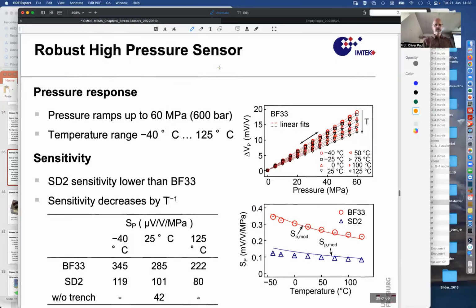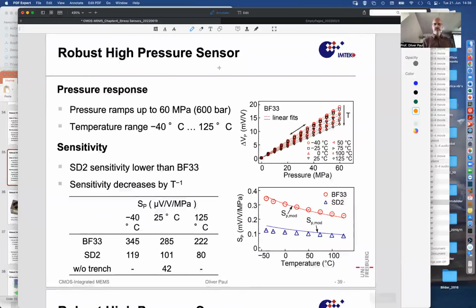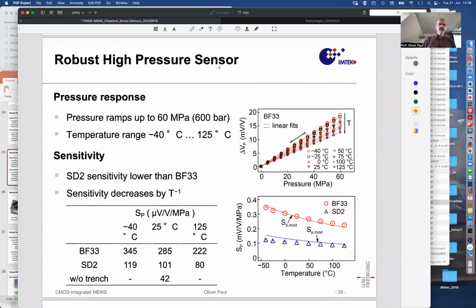Then, of course, many other aspects are studied in such a PhD thesis. Like, of course, now the linearity is a question. So if we go to 60 megapascal, 600 bar, is the sensor linear? And here's the pressure, and then the output voltage of the piezoresistive Wheatstone bridge. And you see that the response is very linear in all cases as a function of temperature. It varies because of the piezoresistive coefficient varying with temperature. Pi coefficient varies with temperature.